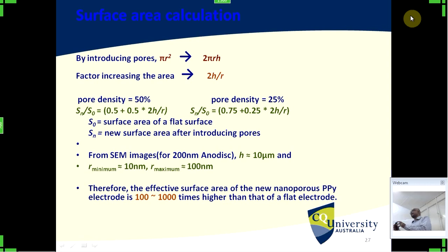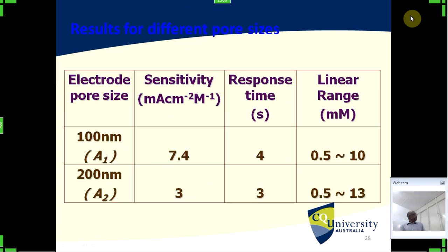This nanotechnology has helped us improve the sensitivity of this sensor while keeping the visual physical size the same. You don't need to increase the physical size, but inside that object you make holes and get area from there. So in this one, for the 100 nanometer one, we obtained 7.4 milliamperes per centimeter squared per mole sensitivity, and for 200 nanometers we got 3, and the response time is short. This works from 0.5 to 13 millimoles. This is more than enough for blood glucose measurements.